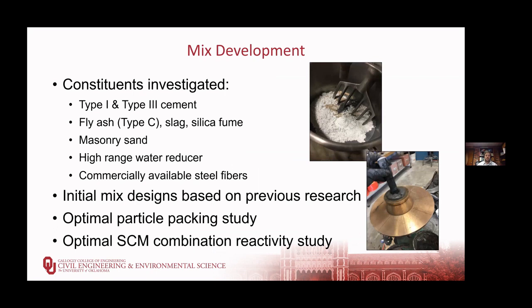So kind of looking at the different things that we've done, starting with the mix development, we looked at a significant number of potential constituents available in Oklahoma, including type 1 and type 3 cement, fly ash, slag cement, and silica fume as our supplementary cementitious materials. We used a very fine masonry sand because we wanted a really small particle size to fill in all the gaps within our matrix. We considered a couple of different high range water reducers as well as different commercially available steel fibers. We started with some initial mix designs that were based on previous research from various groups across the country.